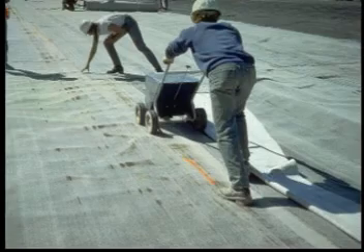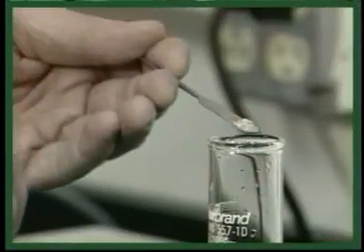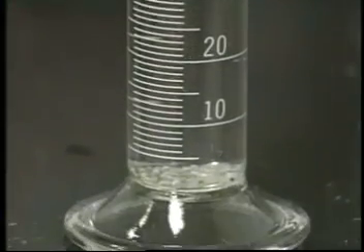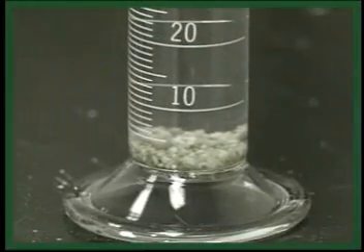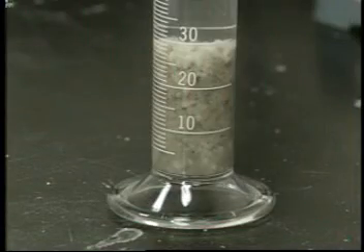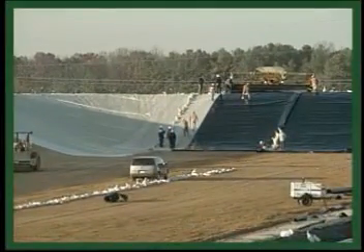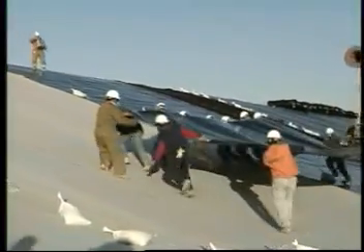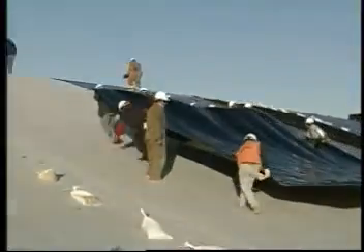Bentonite is very sensitive to water, so Setco's GCLs will hydrate to many times their original weight if they're accidentally wetted before being covered. Therefore, never deploy more GCL than you can cover in one working day. If the GCL becomes hydrated without cover, it may need to be removed and replaced with new material.